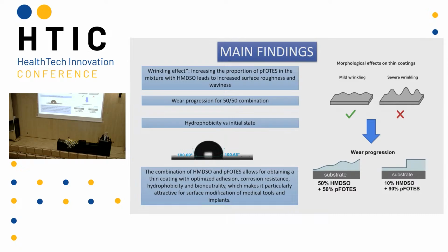We are still working to get the super hydrophobicity in this case, but now I think it's quite a good result. So the main finding is that the combination of HMDSO and PFOTES allows for obtaining a thin coating with optimized adhesion, corrosion resistance, hydrophobicity, and bioneutrality, which makes it particularly attractive for surface modification on medical tools and implants.